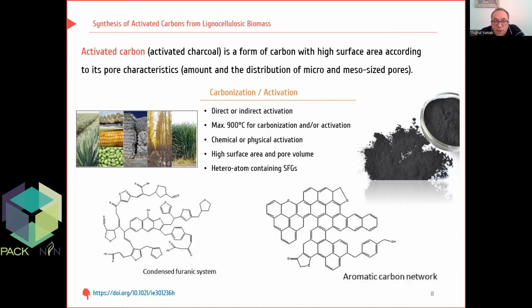In addition, the nature of the biomass and the reactions that occur during the activation process lead to the formation of heteroatom-containing surface functional groups. These groups are very effective in determining the hydrophilic character, so the wettability and the charge of the activated carbon surface.